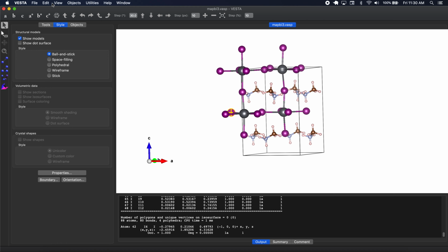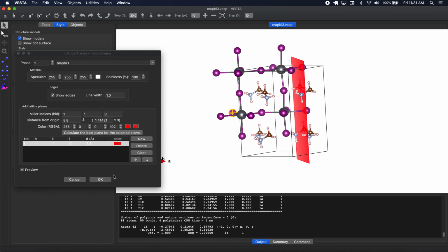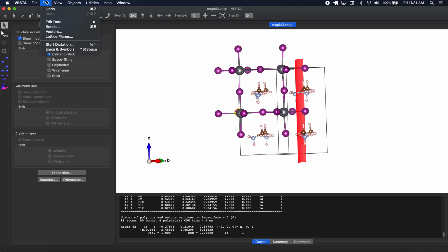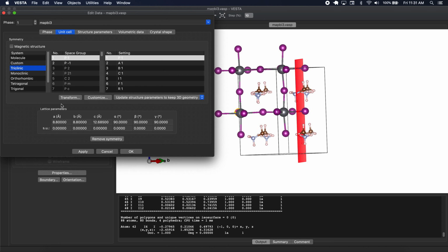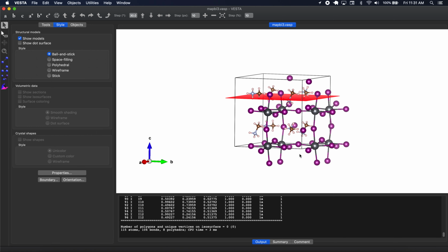Okay, so anyways, the first thing we're going to have to do is cut this 110 plane. So this is actually relatively straightforward. MAPbI3 here is tetragonal. This is the 110 surface. So I'm going to apply this transformation matrix to make this surface now the 002 surface. Okay, so this transformation matrix, if you apply the 110 plane, you can imagine now here I have a vector, 110. Now I take the dot product with each column, I get a new vector, 002.